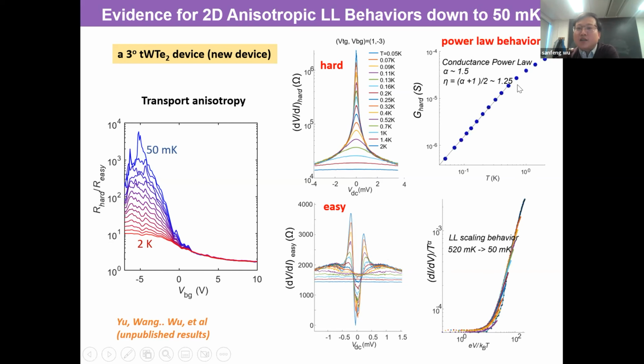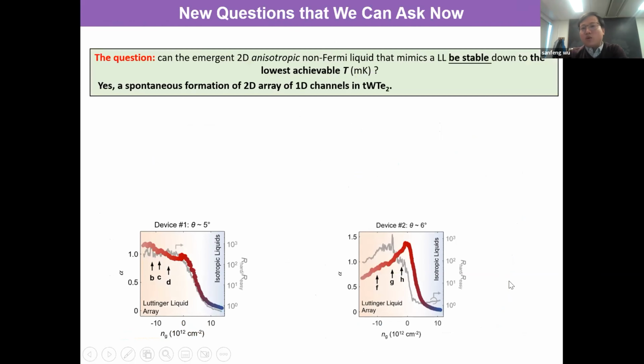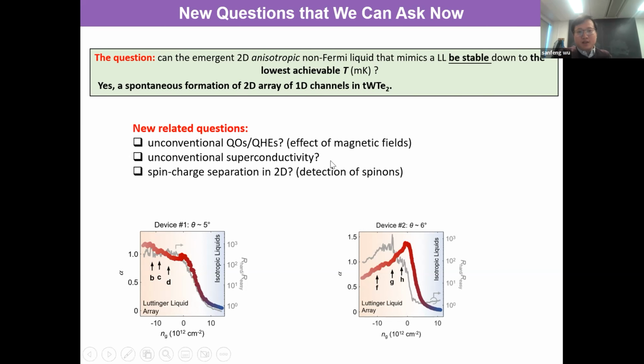And also you can check the power law exponent for this device. So you see a good power law of the conductance, where alpha now is 1.5 in this case, and also scaling behavior quite well. So I think it's a very interesting situation where we can try to answer this question, which is, can you have an emergent two-dimensional Luttinger liquid-like phase down to the lowest temperature? I would say, why not, right? So in this experiment, it seems that at least down to 50 millikelvin, we can have such a phase. And then we'll be very interested to ask what happens next, right?